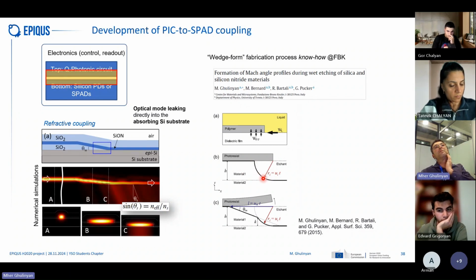It creates a circular profile. And the circular profile is not good, because if you then put your waveguide on top of this, it will be very abruptly changing the profile, and you will have a lot of scattering of light, and that is not good. But when you have the possibility to also remove your resist little by little, like peeling off from the substrate, the etchant penetrates underneath, because of capillary phenomena, and it etches also starting from underneath the photoresist.